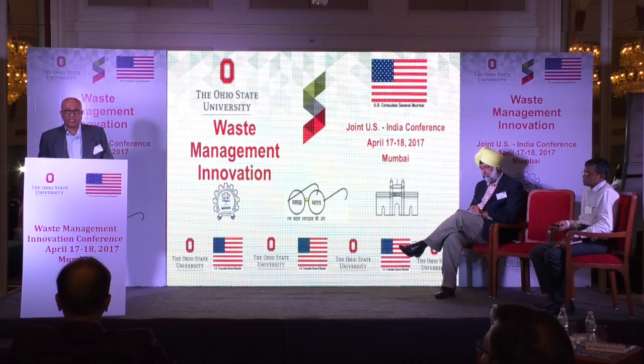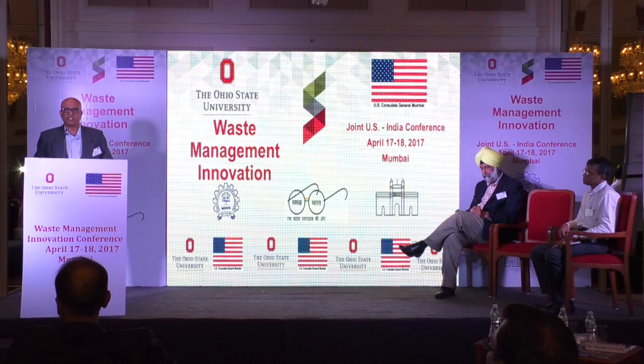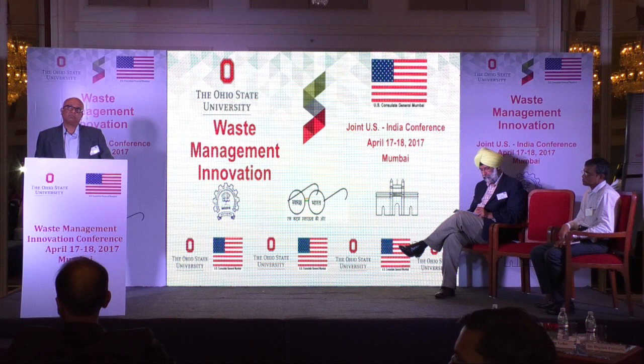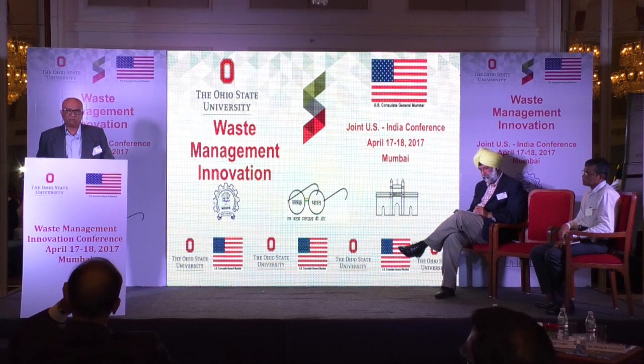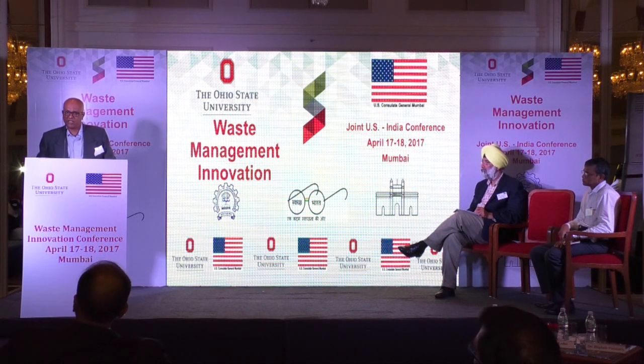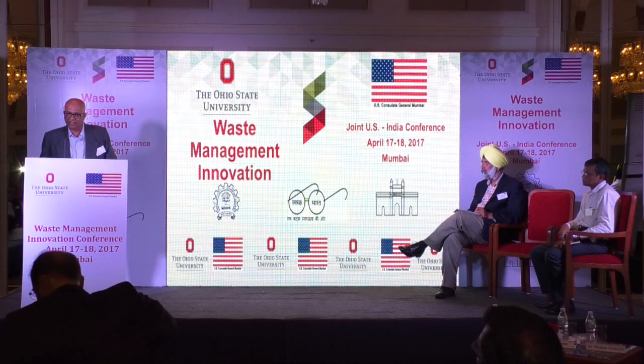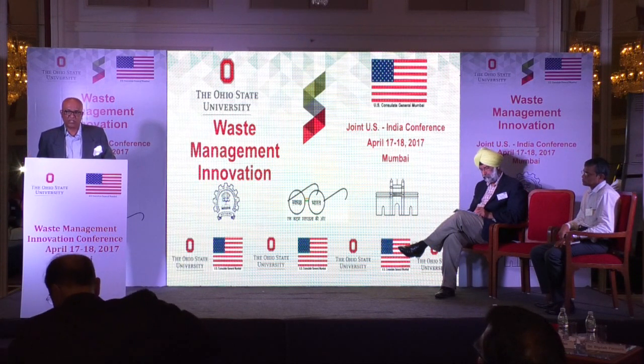We also worked with one of the CSIR institutes of India, and we made geopolymeric cement. Now, geopolymeric cement sets very fast, as compared to other cement. Within 48 hours, a road is ready. It's ready to be driven. So we again took our ash, this time our Indian coal ash. We made geopolymeric cement, we made concrete, and we again built a road of slightly more than a kilometer within our premises, and it's been subjected to heavy traffic, with coal trucks moving on it.